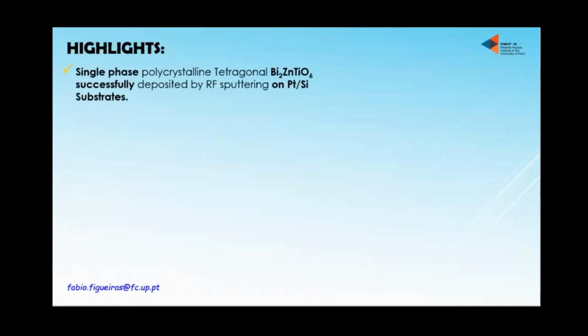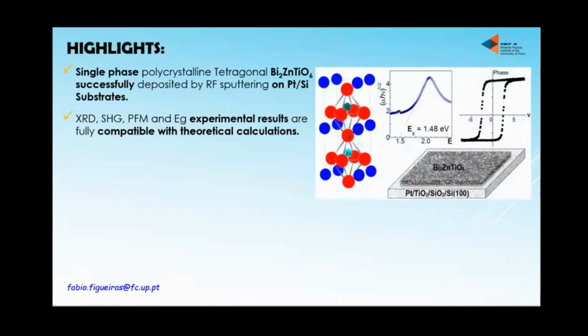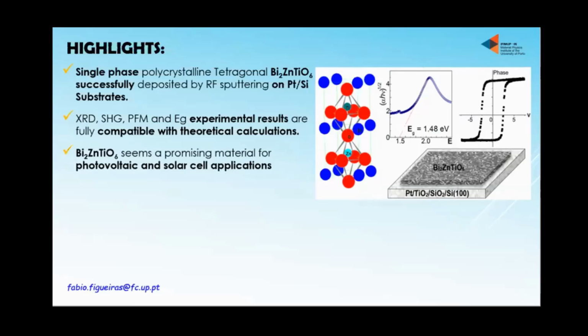So to finish my presentation, my highlight is that you are able to produce a new material, let's say, that material that was predicted by DFT. It is not easy to fabricate ceramics, so we produce it by RF sputtering onto silicon-based substrates. Our many experiments in characterizing these films show that this phase that we got is the predicted bismuth zinc titanium oxide double perovskite. And now we go for the second part of our work, searching for an application and trying to do a prototype on this material. So thank you very much for your attention. I hope you have questions, please.